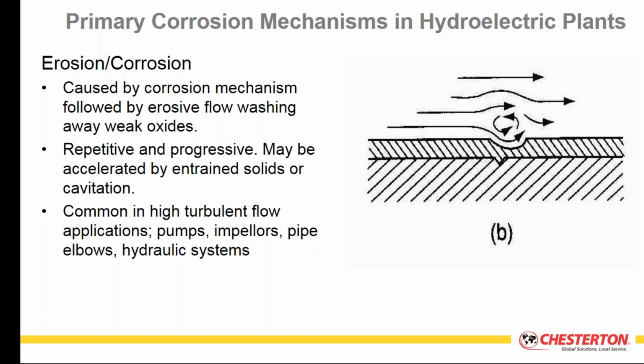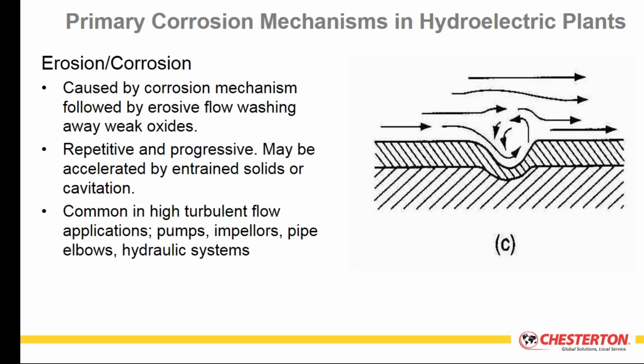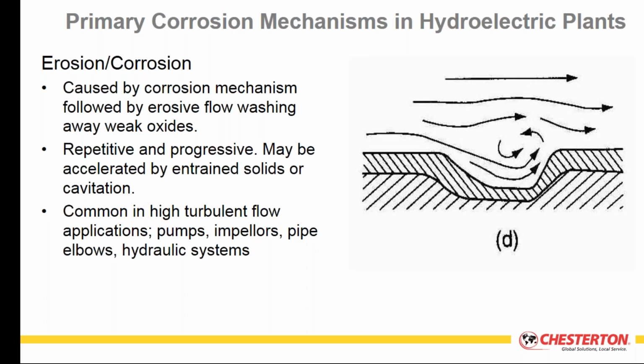This progresses over time until eventually the oxide layer is removed, and now I'm starting to remove the base metal because that base metal is repetitively oxidizing, and then that oxide layer is being removed, and the cycle repeats itself over and over again. Eventually, you will see accelerated erosion factors occurring in localized regions, and these are areas of specific damage that we need to be able to address.